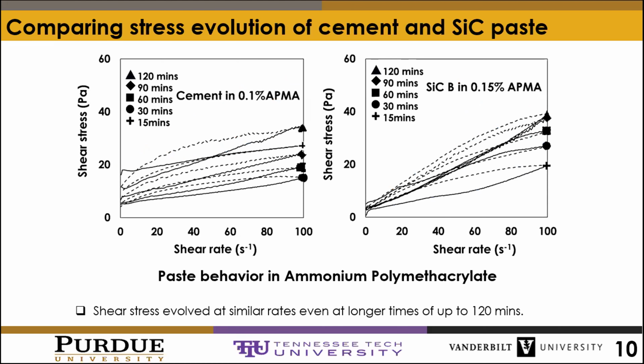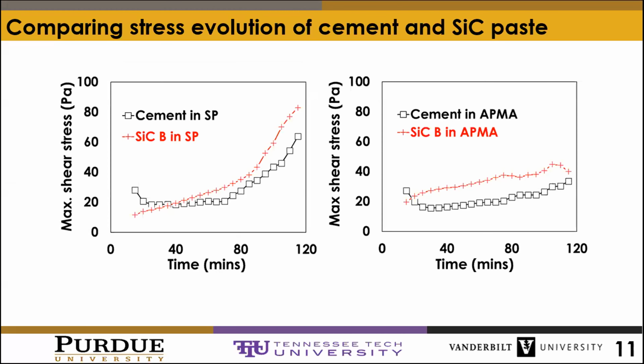The same comparison is true for both solids, even at longer times of up to 120 minutes, suggesting that the difference in the time evolution of the hysteresis curve under flow conditions is not due to hydration alone, since silicon carbide is a non-hydrating system. Here is the maximum shear stress attained in each cycle loop against time for both pastes in the two liquid treatments. And we see that both pastes evolve to similar shear stress values.